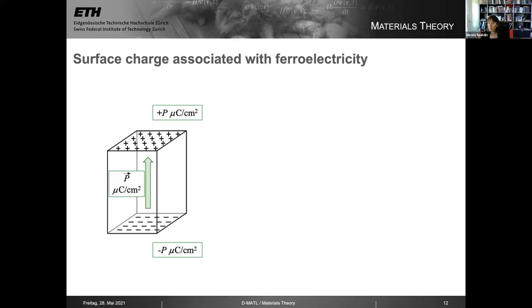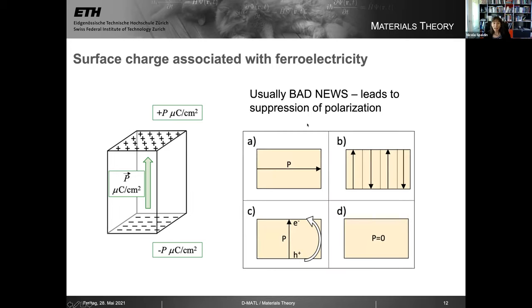So this surface charge is very nice if you're, for example, interested in catalysis or electrochemistry, because a surface charge makes a surface reactive. If you want a stable ferroelectric device, let's say you want to store information in the direction of the polarization, having surface charge is very bad because, by Gauss's theorem, this is electrostatically unstable. There's a discontinuity in the electrostatic potential, a diverging electric field. Particularly when you have a very thin film, so that these surface charges can be large relative to the volume and very close together, this can be very detrimental to the behavior of a ferroelectric. And so what can happen is usually bad news. People spend lifetimes trying to figure out how to compensate this surface charge. So it will somehow try to suppress the polarization.